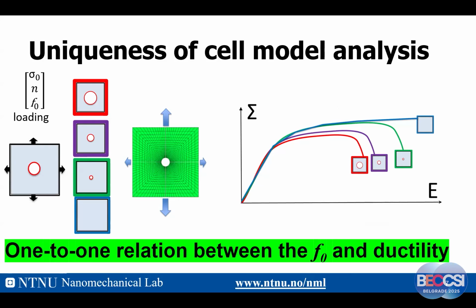Completeness. Then the cell model is also unique. If we try different void volume fractions, on the left you have blue, red, purple and green. So different F0, then you will get different ductility, right? So this is unique. There is a one-to-one relation between the initial void volume fraction and ductility. That's important. So for cell model analysis, we have both the completeness and the uniqueness.